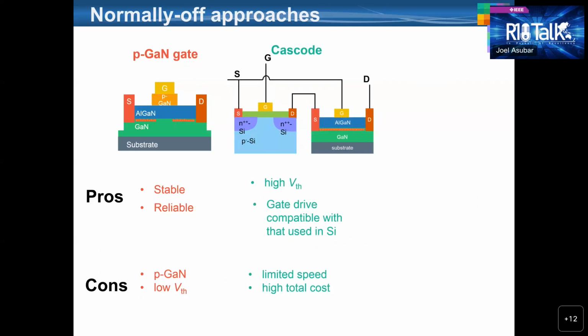Another approach is the cascode structure. For a cascode structure, a normally off silicon device is used in tandem with the gallium nitride device. The VTH of this silicon device dictates the threshold voltage of the overall device. Its advantages include high threshold voltage, and the gate drive is compatible. The gate driver is compatible with that used in silicon IGBTs. However, its disadvantages include limited speed. Gallium nitride based devices are popular because they can switch at very high frequencies. But because we are using silicon, again, the silicon limits the speed of the device. And of course, because we are using silicon and gallium nitride together, it will result in higher total cost of fabrication.